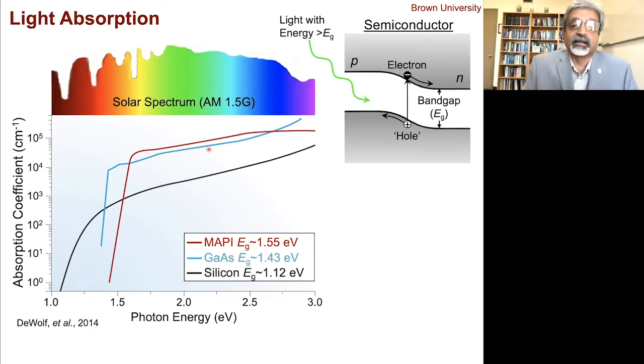This is your Ferrari of photovoltaics, gallium arsenide. And look at MAPI. This is the perovskite, which is actually made in sort of quick and dirty way, has even higher light absorption compared to gallium arsenide. So this is enough for people like us to dance in the streets, this tremendous light absorption. This is key to making good solar cells, is the good light absorption.